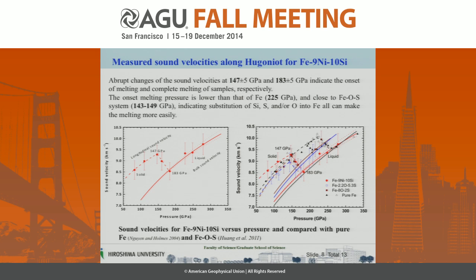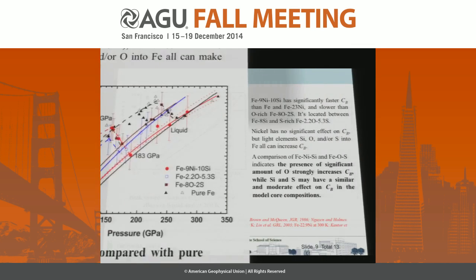When we compare our results with pure iron and the iron-oxygen-sulfur system, we can see the onset melting pressure of our sample is significantly lower than pure iron and close to the iron-oxygen-sulfur system, indicating that substitution of silicon, sulfur, and oxygen into iron can make the melting easier.